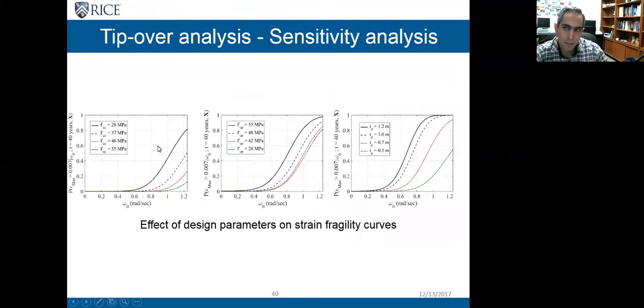The meta model was also used for sensitivity analysis, and in these plots I'm showing how the response reacts to variations in the compressive strength of the concrete in the overpack, and also pad parameters. Looking at the compressive strength of the overpack, we see that for a stronger concrete in the overpack, smaller failure probabilities result. But when we look at the pad, any change which makes the pad stiffer applies stronger forces to the cask, which leads to an increase in the probability of failure.